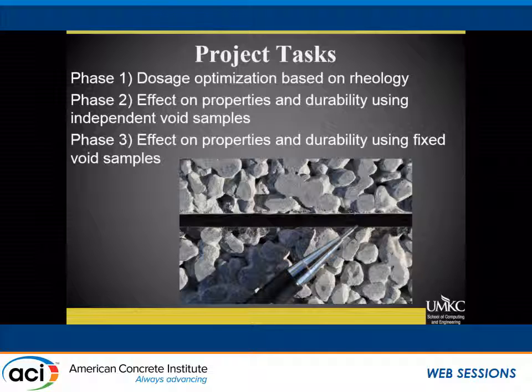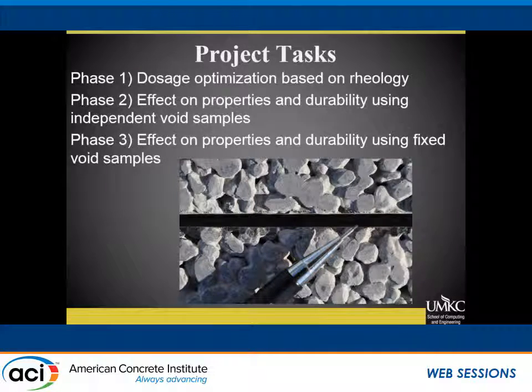So you want to optimize the cementitious paste, especially one that we know can get quite sticky at higher dosages. And in pervious, if anybody's placed pervious, we know that when it gets sticky, you start getting in trouble because you can't get sufficient compaction. It tends to dry out. The workers can't get it placed quick enough, and you're in trouble. So we say, all right,